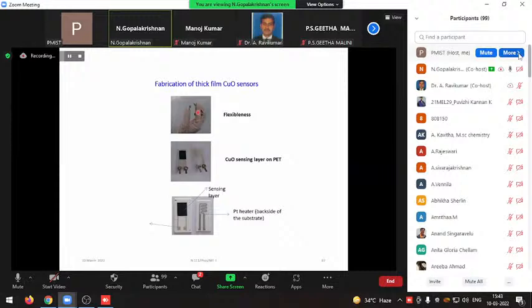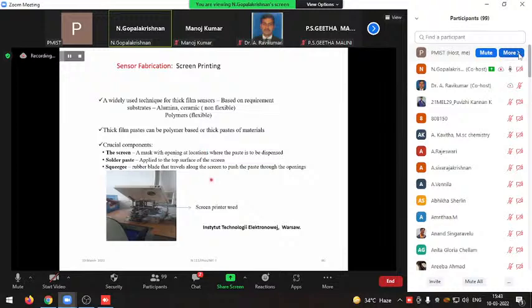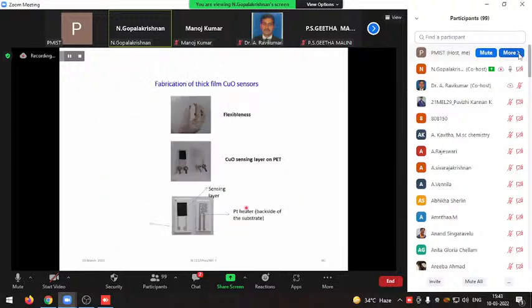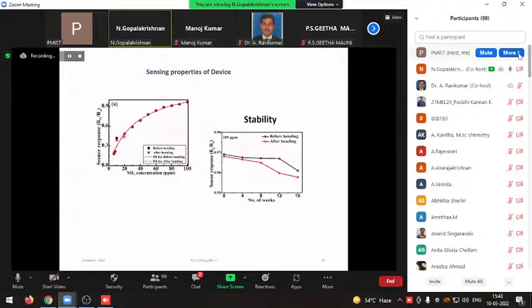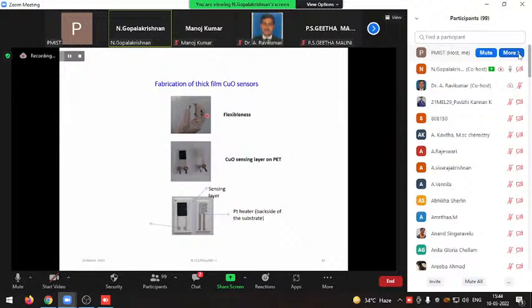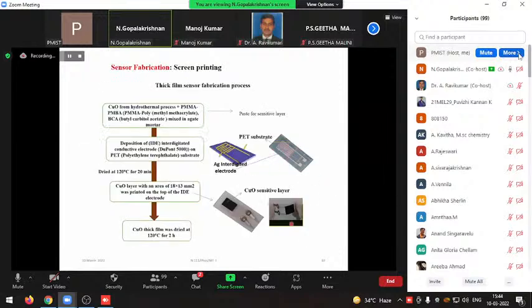See here, our sensor is more flexible because of the PET substrate. The same thing shown here is again shown here. It is a more flexible sensor, and we measured the sensor response before bending and after bending. We bent the sensor like this and kept it bent for some time, 15 minutes, 20 minutes, some hours, or 1 day. Then we checked the efficiency.